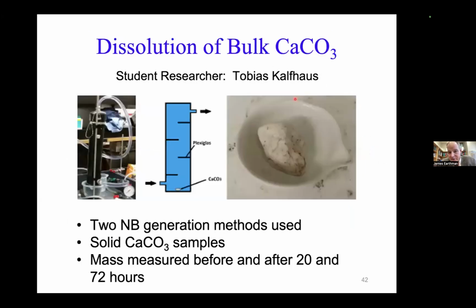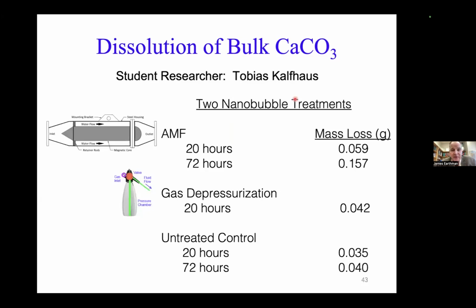All right, we did some experiments to check this. Here we took some solid calcium carbonate. We added DI water. We put nanobubbles in some of our experiments. We had untreated controls, and after 20 hours, you can see the mass loss of the calcium carbonate was 0.059 here. For the untreated control, it was 0.035. This is nanobubbles created from the gas depressurization, a little bit higher, but not that much compared to the AMF system. After 72 hours, we had a mass loss of 0.157 grams, and in the DI untreated water, we had 0.04. Not much change here.